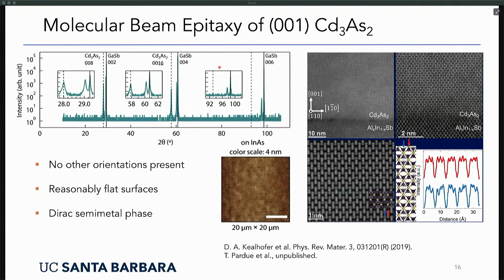As I mentioned, the 001 orientation is a little bit more difficult to grow. But David, the student who did this work, managed to grow this by using a wetting layer of indium arsenide, and then it grows a little better. Later we also grew it on a lattice matched buffer layer, and you can see the high resolution cross-section TEM images here, atomic resolution images, showing that we have also grown the cadmium arsenide in the right crystal structure. And that's an image of the surface, so it's fairly smooth. It's not as atomically stepped as the 112 surfaces, but it's fairly smooth.